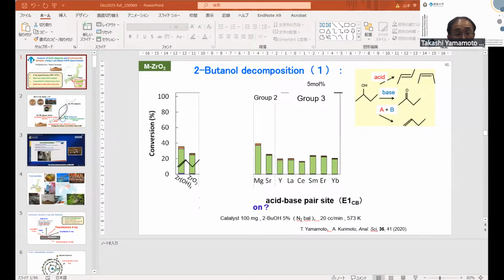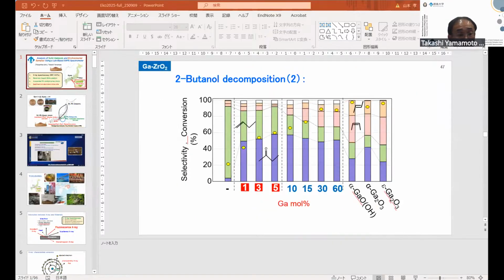Next, we changed the doping amount, and this is the result. This means the doping amount is 0, 1, 3, 5, 10, and more mol percent. And this is gallium oxide. The yellow circle is conversion. This is product selectivity: the purple is ketone, the dehydrogenation product, and the green is the common olefin. You can see that with a small amount of dopant, 1 mol percent addition, the conversion enhanced two times.